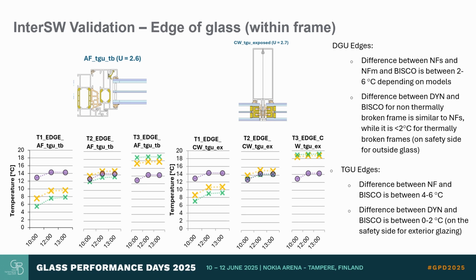When it comes to the edge, I'm just showing the results here for triple glazing units. That's where we don't have a model in the national standard, the French standard. For thermally broken insulated frames and for a curtain wall with exposed edge, we did this analysis for 9 different frame configurations, with also different edge configurations. What you see here in green are the results from the FEM analysis. In violet are the results from the French national standard for the edge temperature, while the yellow is the model that we elaborated, based on FEM but a 1D model, that is very close to the finite element thermal analysis results.